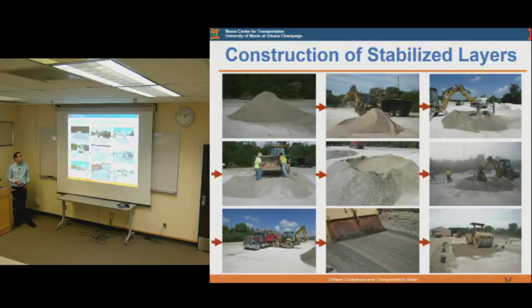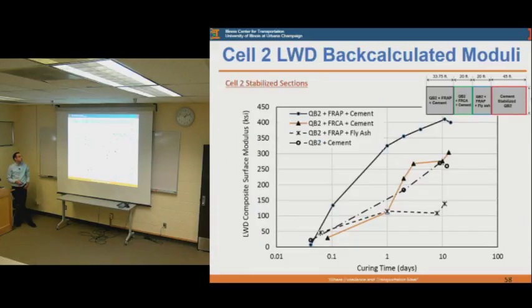Just quickly showing how we constructed, or how we dealt with, the stabilized layers for these test sections. Because we were constructing very small test sections, we did manual mixing. We had the stockpiles of the materials, and then we were mixing the stockpiles very well with a bucket of a backhoe, adding the cement percentage as required, then mixing again, and then adding the water percentage as required. So we were measuring the moisture content before and after, and then mixing again, moving to the construction site, tilling several times in order to get uniformity, and then compacting the test sections and checking the heights and the elevations and everything. This is also something that we did while we were constructing, before the HMA was paved on top of the test sections.